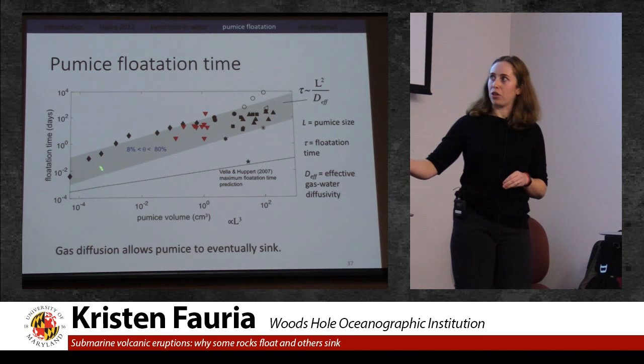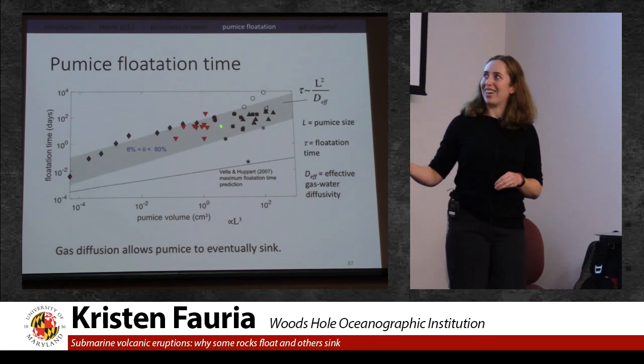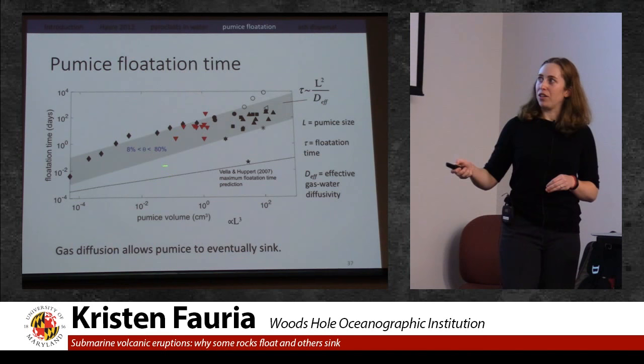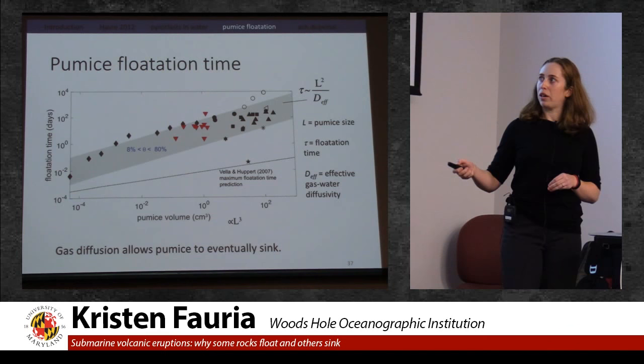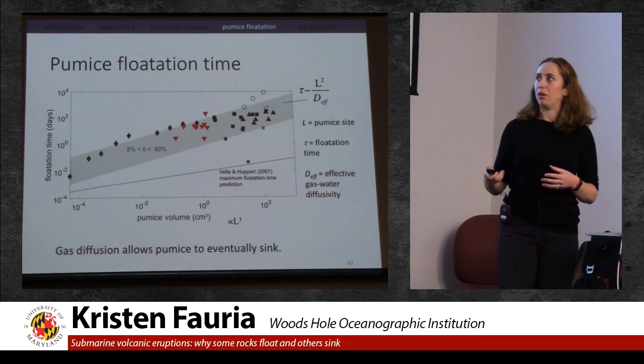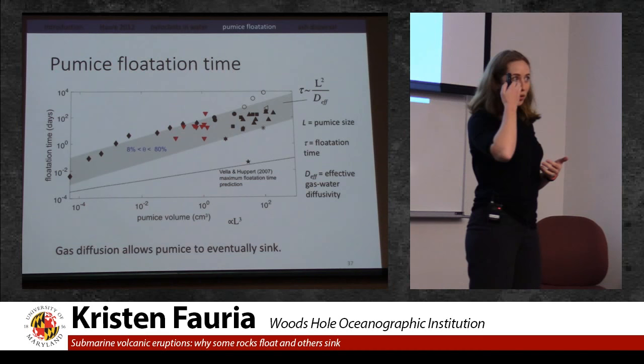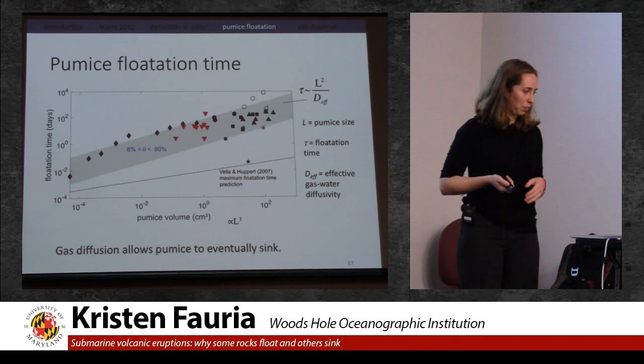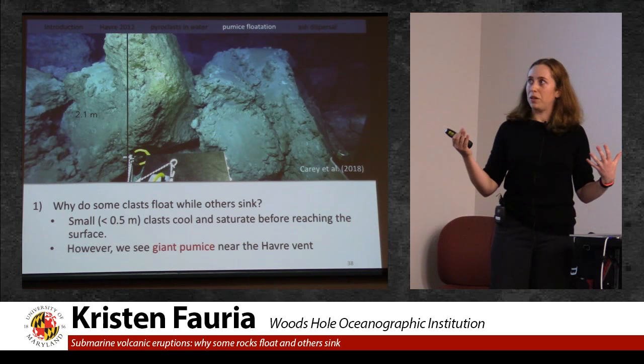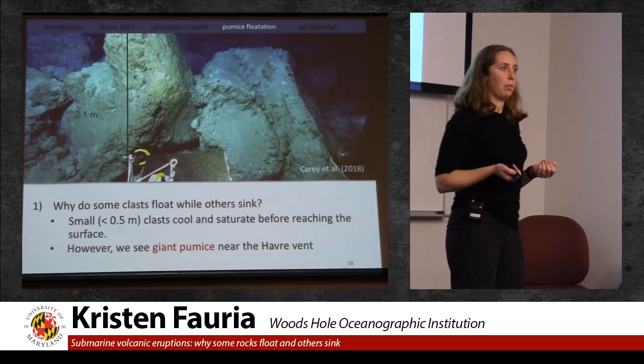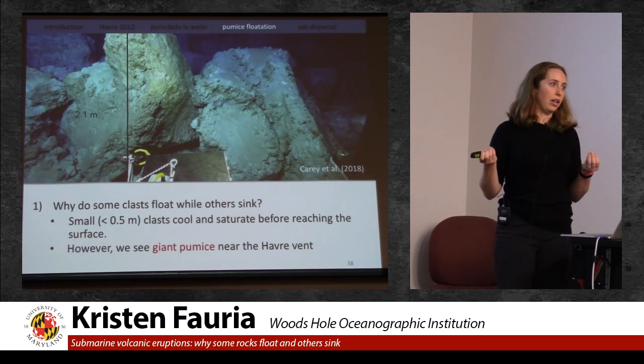And actually, the red data are mine in this case, and the black data come from the literature. And this is the original prediction from the Darcy flow model in the beginning of the talk, and then the gray band represents a diffusion prediction. We find that the time scale of flotation scales with the length squared, which is consistent with diffusion controlling the flotation of these pumice. And so we know that pumice is able to float because it can ingest air, or has some non-condensable gas that's held in via surface tension, and sinks because of gas diffusion.